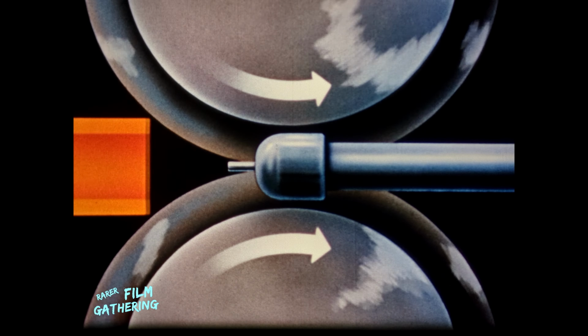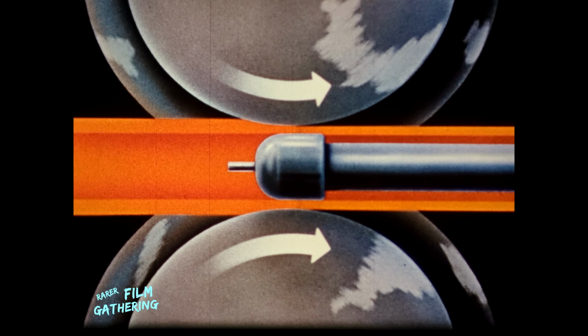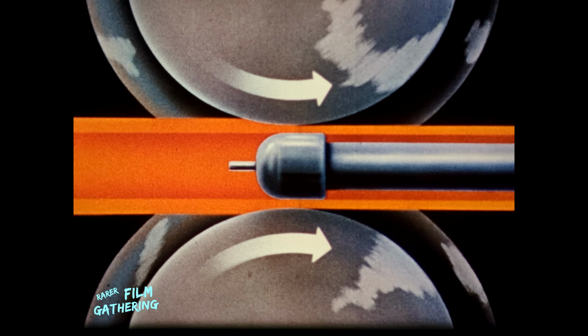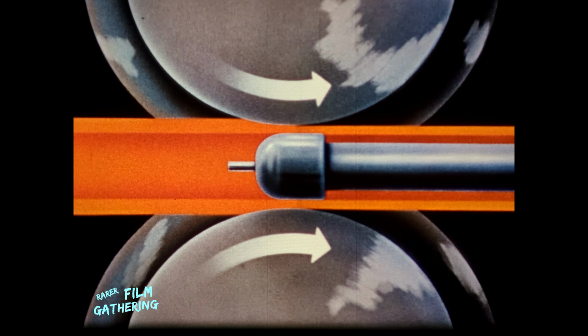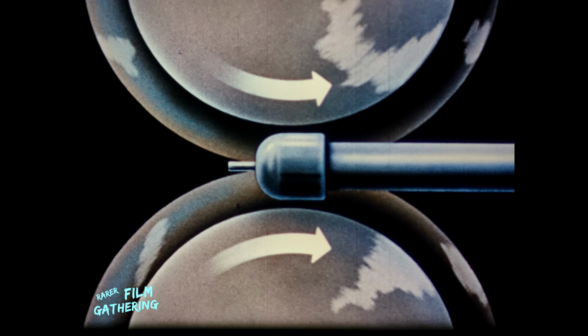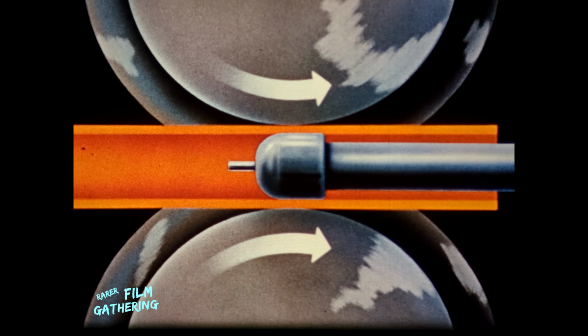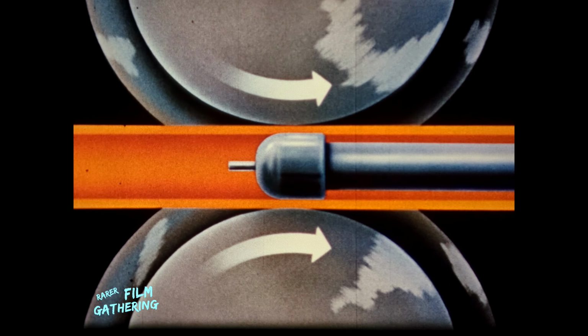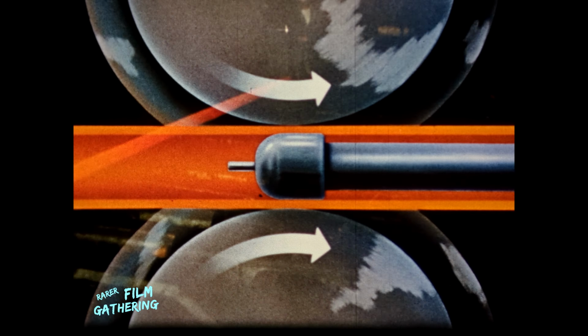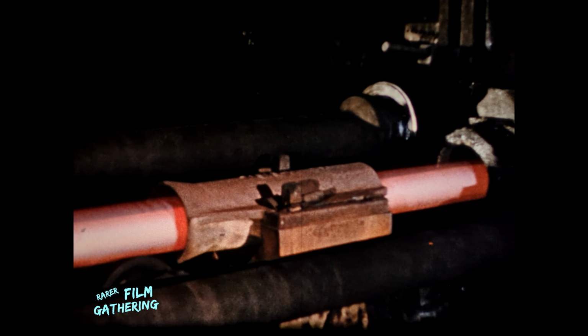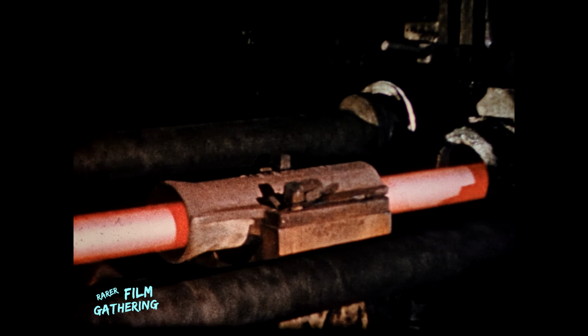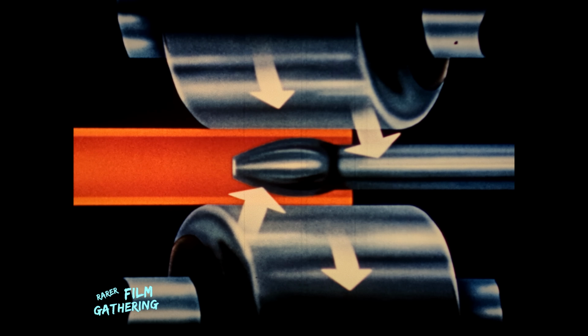After the piercing operation, the tube is passed over a blunt-shaped plug in the plug mill, which substantially lengthens the pierced hollow, reduces its wall thickness, and slightly reduces its diameter. A second pass is usually made using a slightly larger plug to ensure a uniform wall. After this operation, the original short tube round has been increased in length to the approximate finished length of the pipe. Reeler rolls help to finish the pipe. They do the work on the outside, while a mandrel bar holds a reeler plug to finish the inside surface.